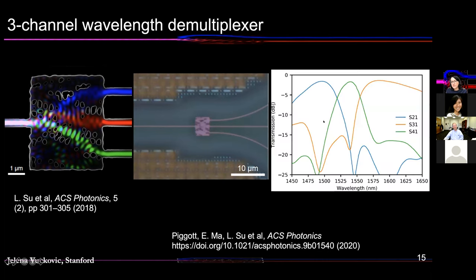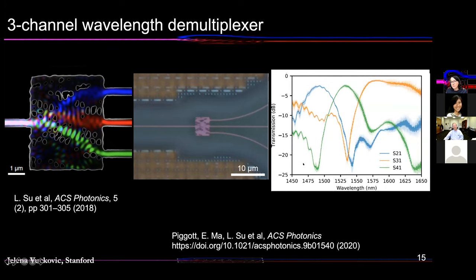This is the predicted behavior for transmission as a function of wavelength. And here is the measured behavior for foundry devices. Again, we plot transmission for many devices on the chip that were made with the same parameters, and they line up on top of each other. And if you compare it with the theoretically predicted behavior, the correspondence is pretty good. There is a minor discrepancy, which comes from the fact that when we sent these first devices for tape out, we sent them with minimum feature sizes of 80 nanometers, but it turns out that for AIM Photonics, minimum features are more like 100 nanometers.